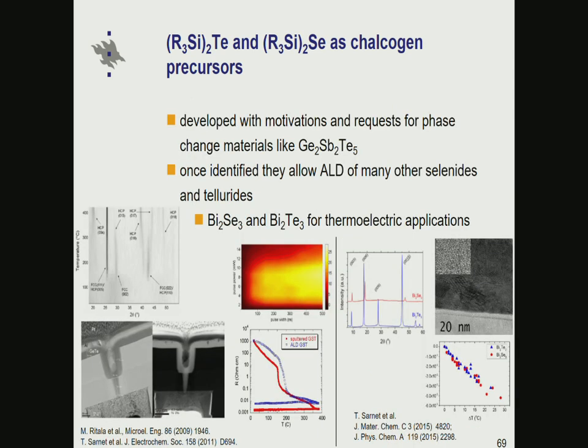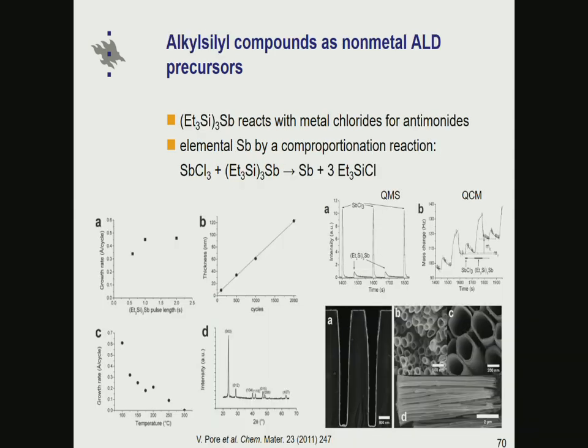It was developed with motivations coming from germanium antimony telluride. We studied that further, also the material properties with IBM, and the functional properties are as expected, similar to the sputtered counterparts, but with the added conformality of the ALD technique. Once we have the chemistry available, it could be extended so that, for example, bismuth selenide tellurides could be deposited for thermoelectric applications. We went further and also made similar compounds for antimony that react with metal chlorides to deposit metal antimonides.